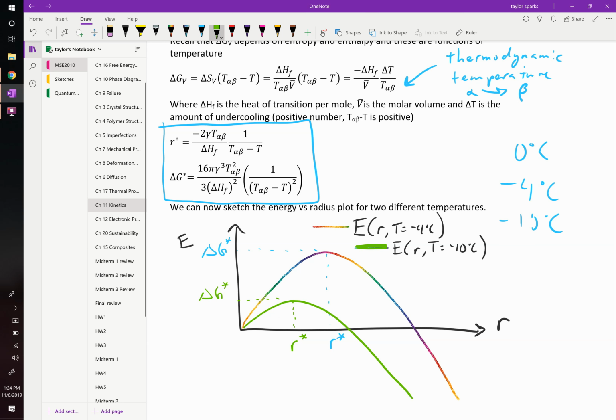So what does this mean? As you're cooling down water, you get right to 0 Celsius, and you go 1 degree below, and we could draw the line. And it would be a really big R star, and it would be a really tall activation energy, because we're only 1 degree below, okay? If you go 5 degrees below, 10 degrees below, as you increasingly supercool it, what happens is the necessary size of your clump of atoms that won't redissolve again gets smaller and smaller and smaller. And the activation energy that you have to overcome gets smaller and smaller and smaller, which means that if you keep on supercooling something, eventually it's going to solidify because it's getting easier and easier. That bar that it has to clear just goes down and down and down as you increasingly supercool it below its thermodynamically predicted transformation temperature.